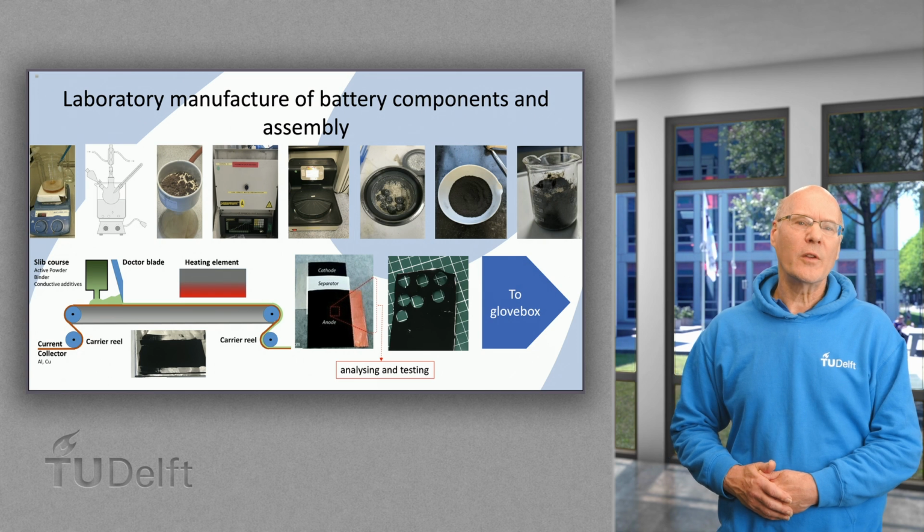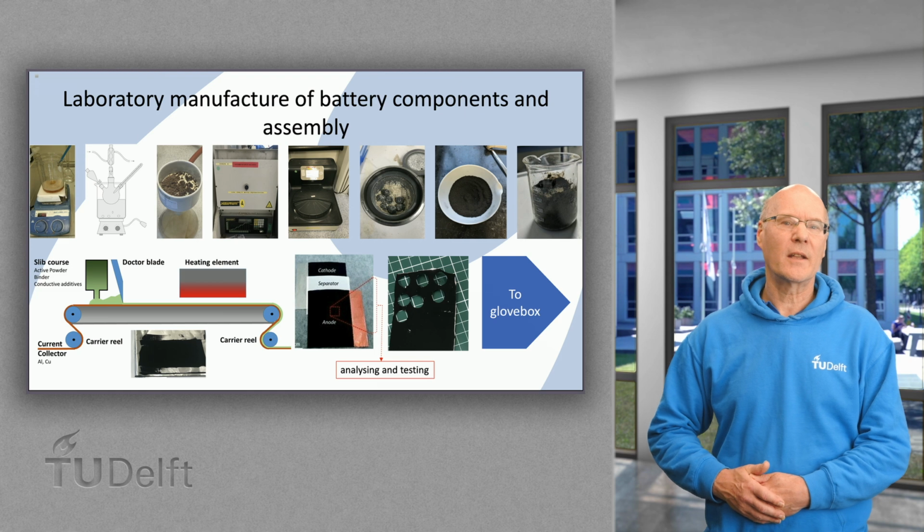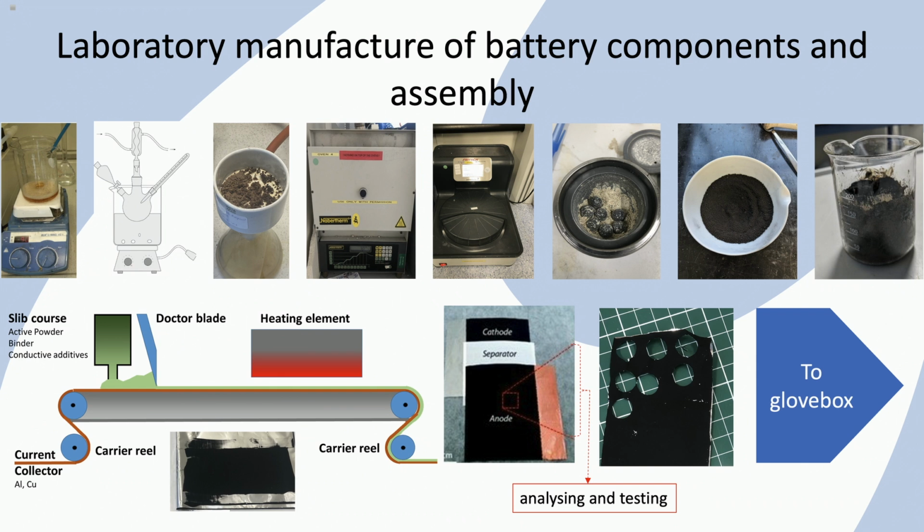This mixture will be further processed by removing the water and fired or calcined at a temperature between 500 and 1000 degrees C. The formed powder will be ball milled and heated another time at the desired temperature. The final product is typically a black powder that will be analyzed on the correct structure and composition, which is not shown here.